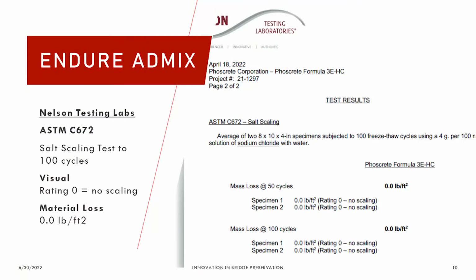Here are the results. You probably can't see it, but the main thing that we want to get from it is that we got a 0 material loss at 50 cycles and a visual rating of 0 for no scaling. We asked the lab to run 100 cycles, and we got the same perfect scores. We signed a licensing agreement with the Indiana Soybean Alliance to market Pore Shield under the brand name Phoscrete Endure. As an admixture, not only does it provide these long-term benefits, but we also found that it makes mixing and placing the material that much easier as well.